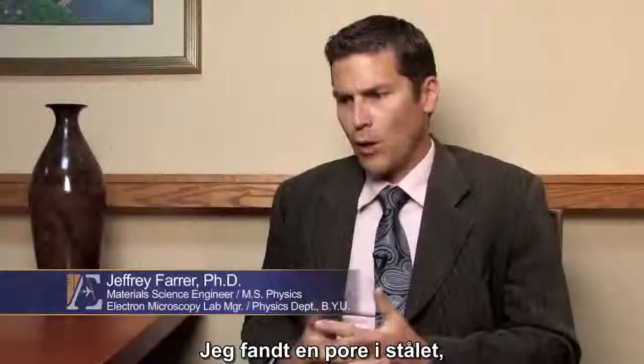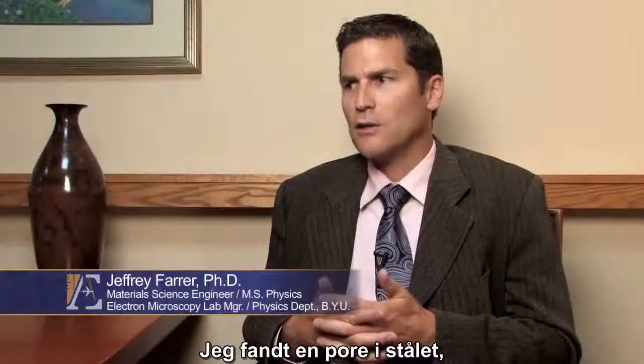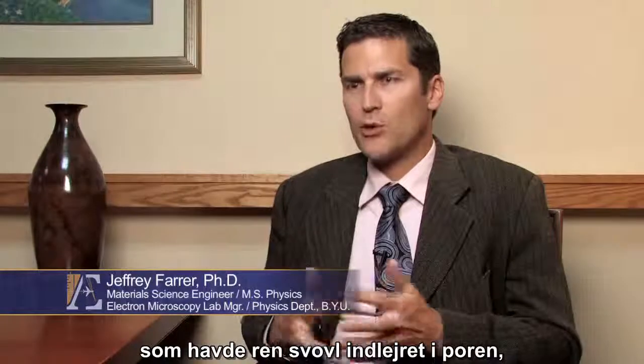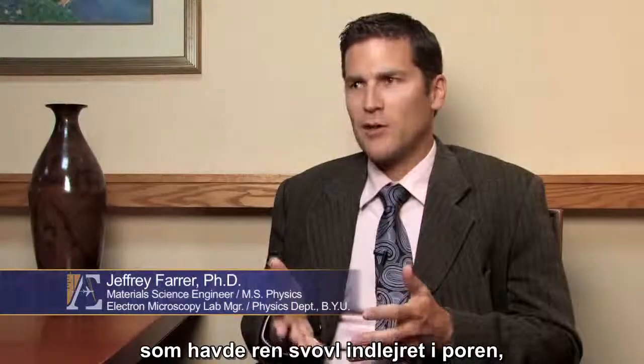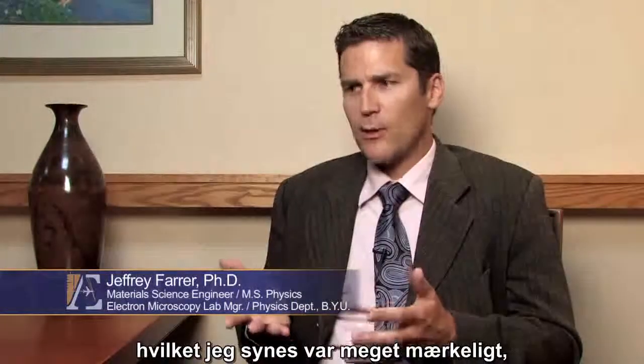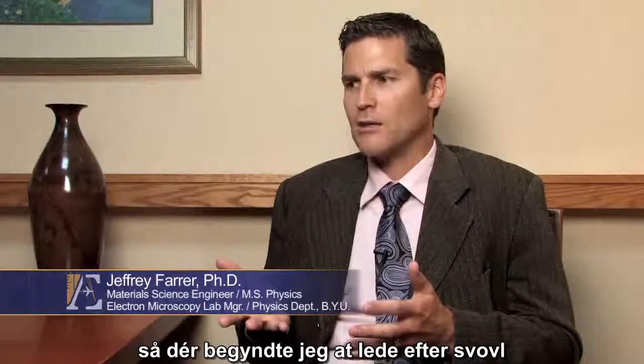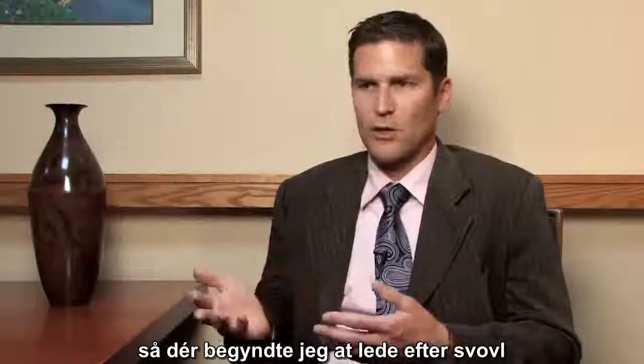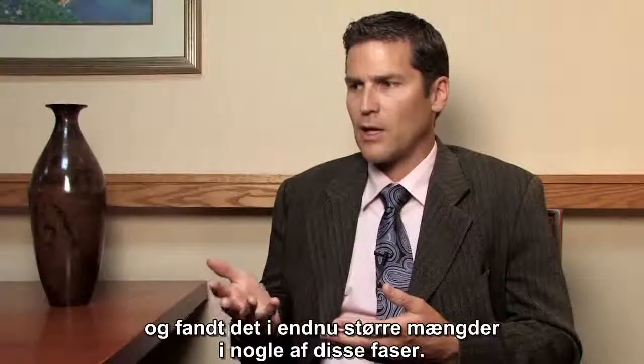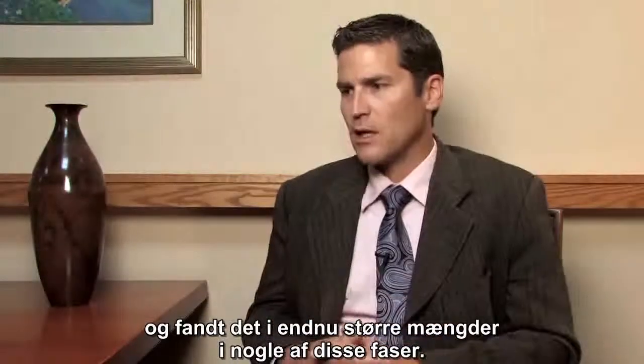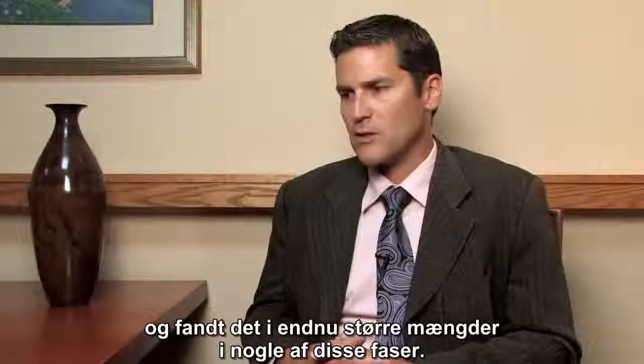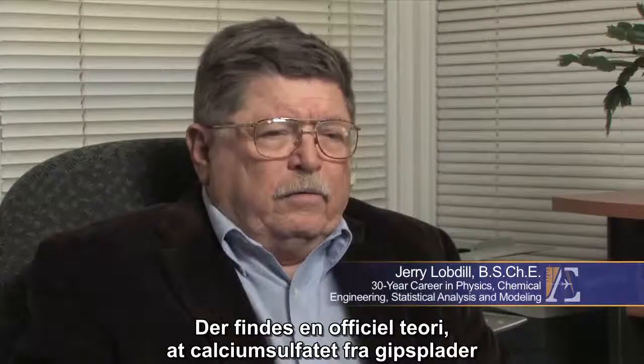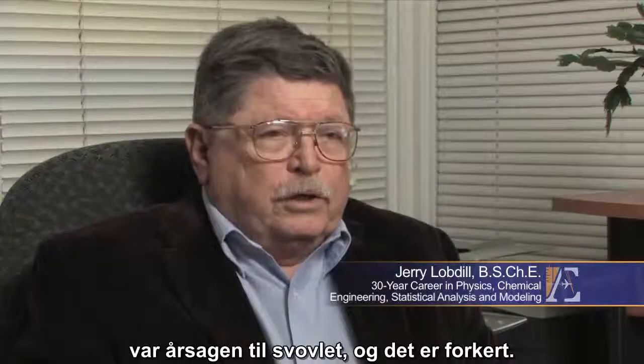the towers. I found a pore in the steel that had pure sulfur embedded in the pore, which I thought was very strange. And so that's when I really started looking for sulfur and finding it in more abundance in some of these phases. There's a government theory that calcium sulfate from gypsum boards was the source of sulfur, and